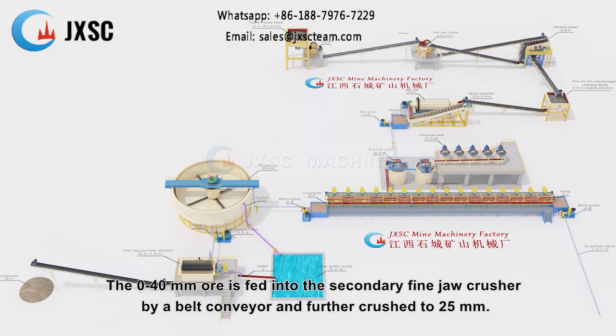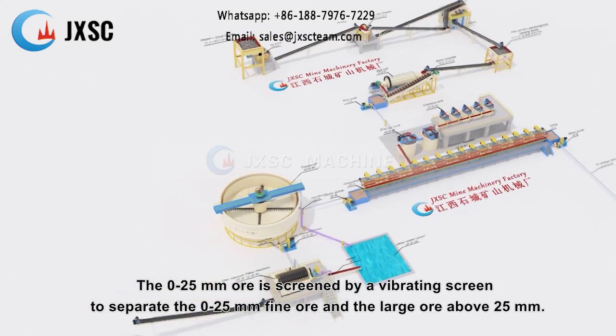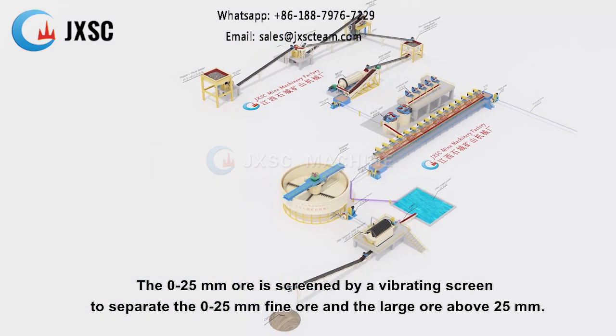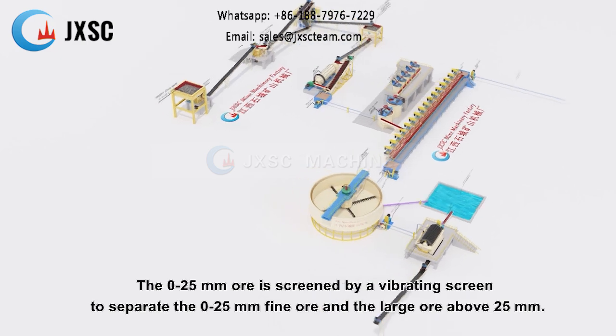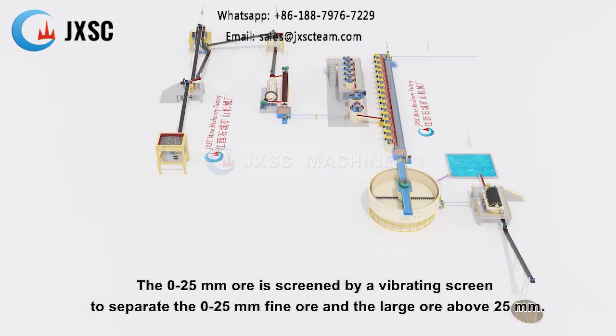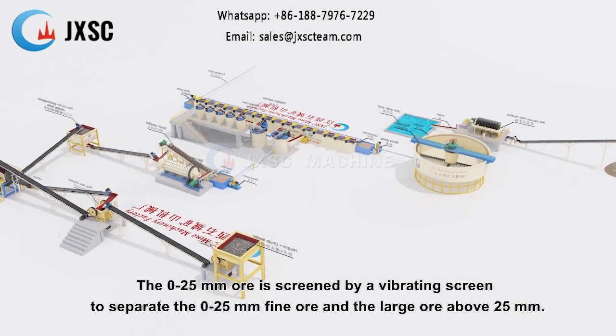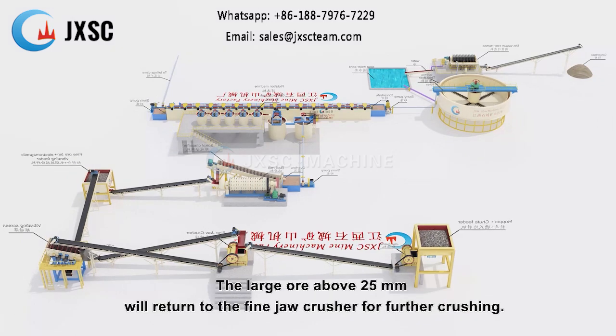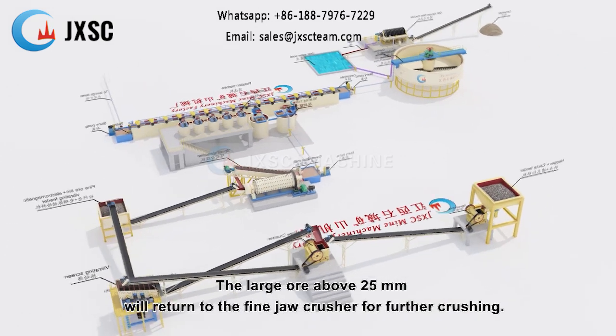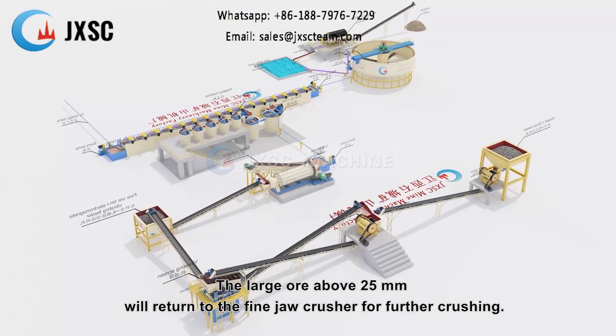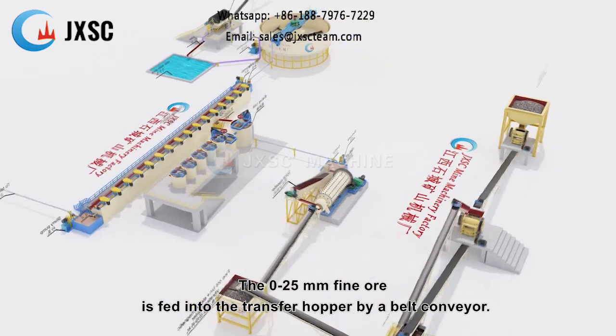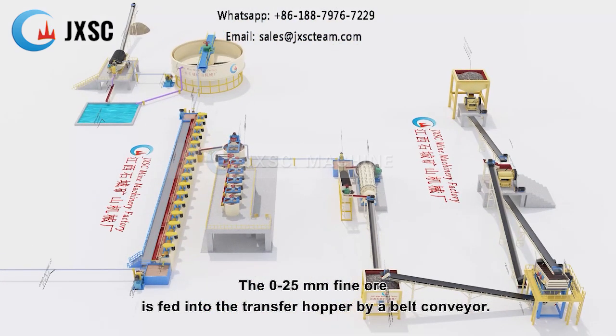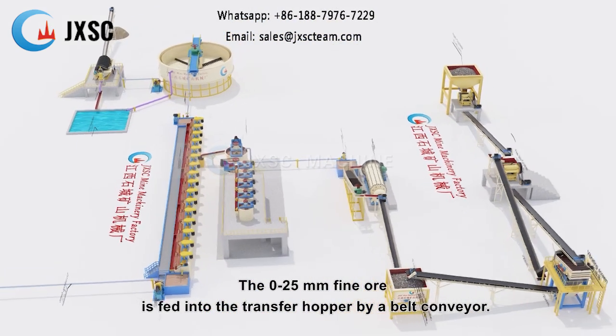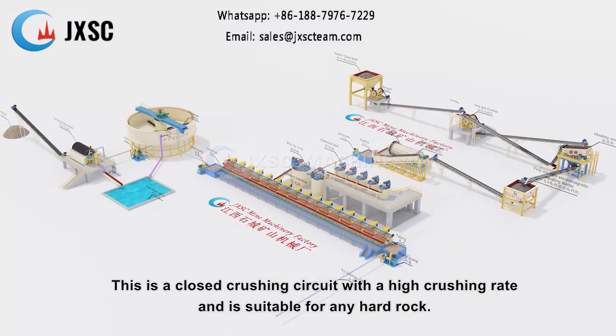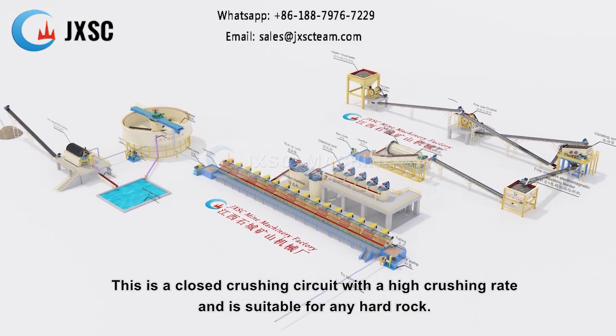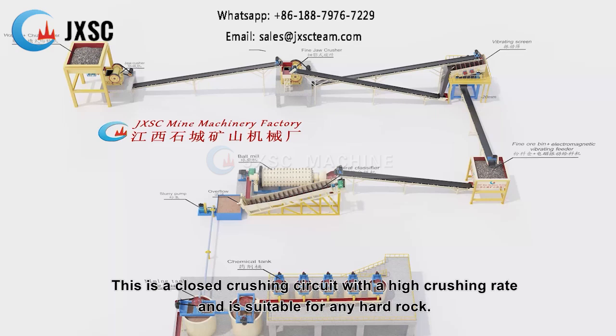crushed to 25 millimeters. The 0 to 25 millimeter ore is screened by a vibrating screen to separate the 0 to 25 millimeter fine ore and the large ore above 25 millimeters. The large ore above 25 millimeters will return to the fine jaw crusher for further crushing. The 0 to 25 millimeter fine ore is fed into the transfer hopper by a belt conveyor. This is a closed crushing circuit with a high crushing rate and is suitable for any hard rock.